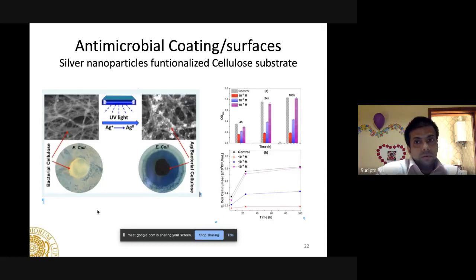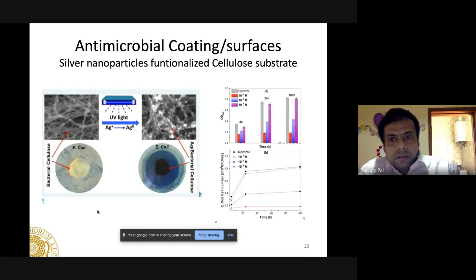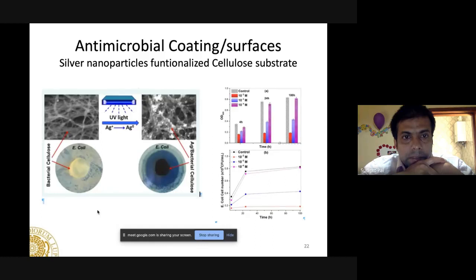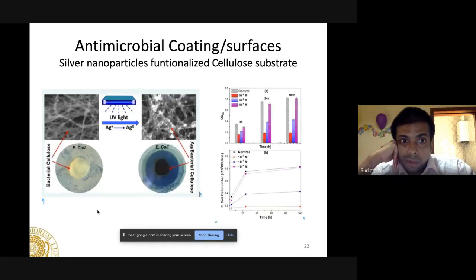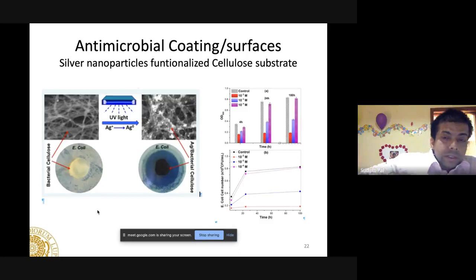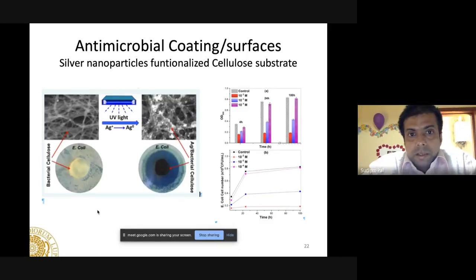Now I move to the nanobiotechnological section, where I will show the activity of antibacterial or antimicrobial surfaces. Usually, copper and silver are very popular and have been known for a long time for their antibacterial activity. But to have practical application, they need to be coated or functionalized onto some other substrate, like any surface or clothes or any other material. So here, what we did, we coated the cellulose substrate with silver, mainly silver nanoparticles.